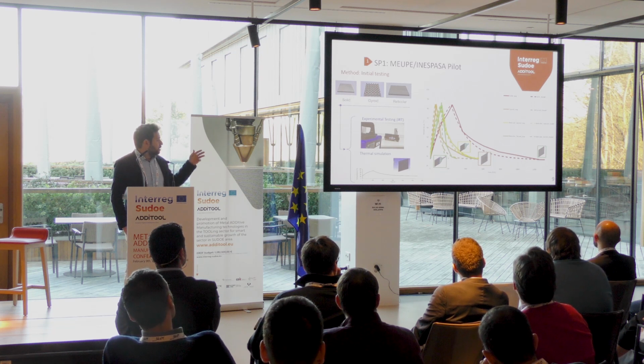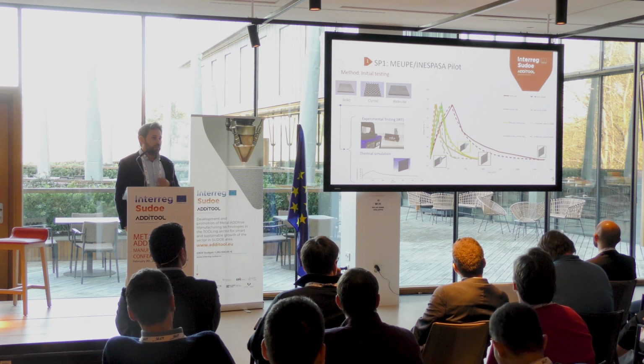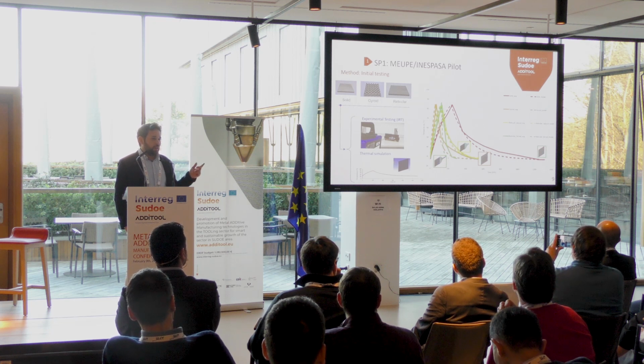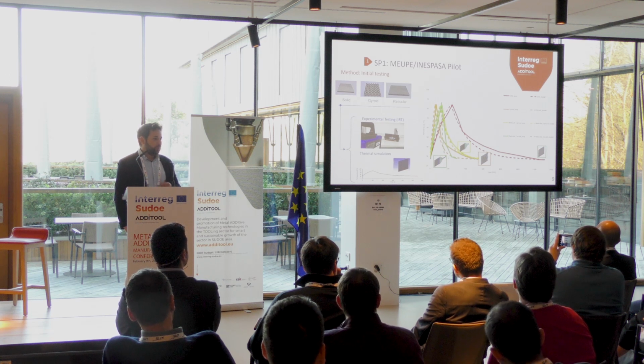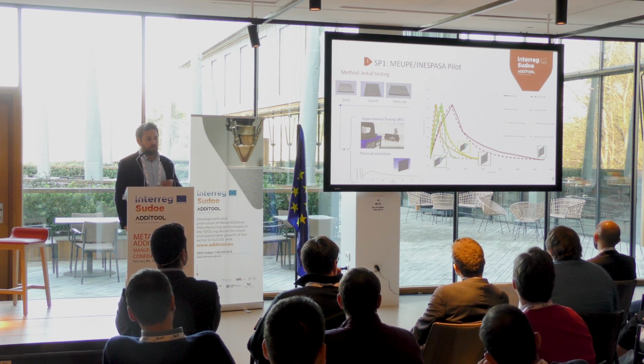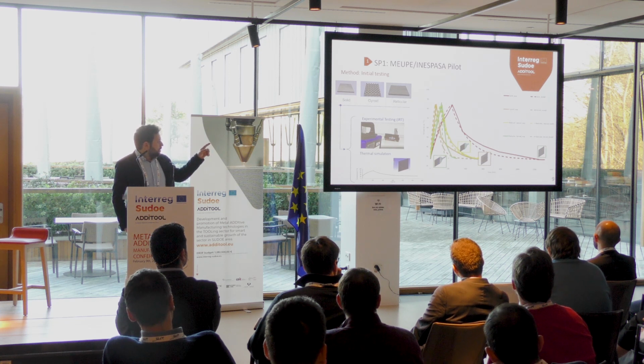We test these 3 samples by heating them till 85 degrees, and with an infrared thermography camera, we monitor the warm-up and the cool-down process. Those are the continuous lines.